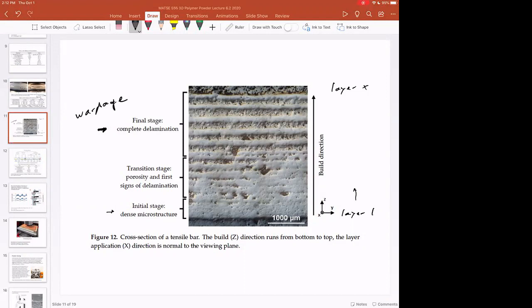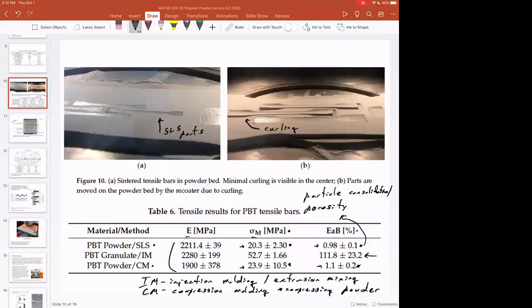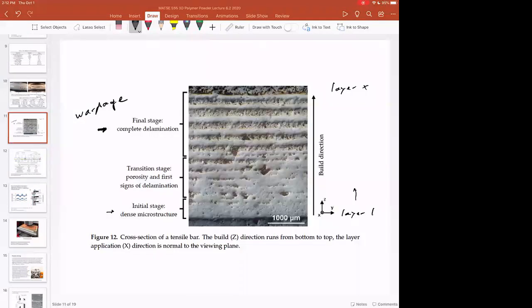So in essence, what's happening is as you're coalescing this powder, the part is starting to warp, and then the machine is getting out of register in relation to where the part is, and you start to get this partial coalescence. And so as these parts, let's go back to the image, as these parts are moving around on the powder bed, or as you're getting more and more coalescence, you can get different sorts of defects as you make the structure thicker and thicker and thicker.